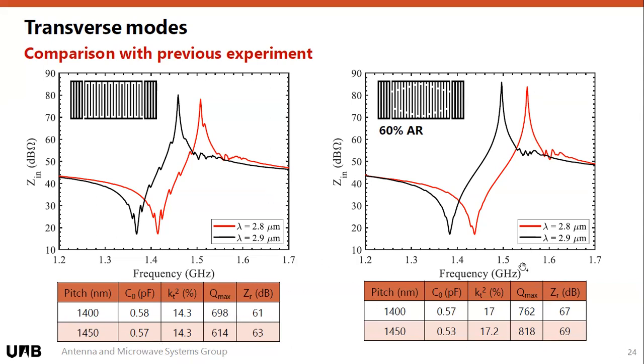So we have jumped in Q by around 200 and in coupling too. We are confining the mode better. We are more efficient at transducing energy from the IDT into the SH0 mode. We are not losing energy into the transverse modes. So actually, we had a 14% KT squared, we now have a 17% KT squared. This is a really high value if you compare it to the ones we saw at the beginning.